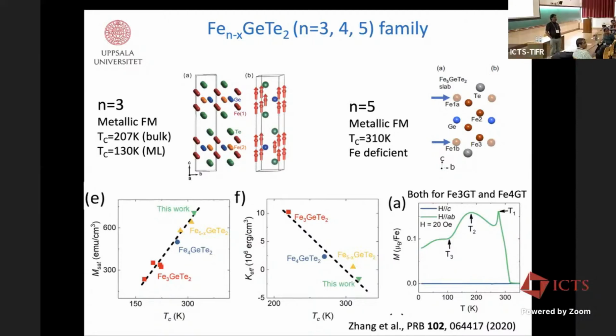Because without that, you are in the loophole of the Mermin-Wagner theorem, and you do not expect to see long-range order in 2 dimensions. You need to break that isotropy in the Hamiltonian. That's why magnetic anisotropy is very important, which breaks this isotropy. And the strength of the magnetic anisotropy energy dictates how well you can stabilize the magnetic moments at a finite temperature. If the value is very small, any thermal fluctuation can kill it. So you need a sizable amount of magnetic anisotropy.